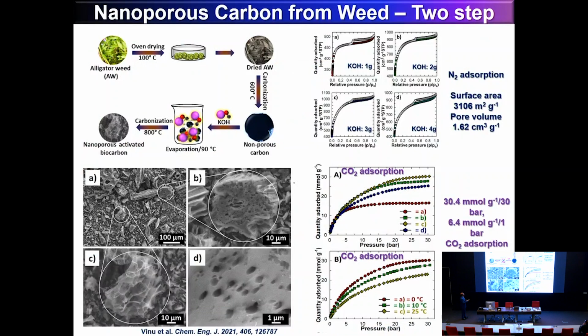When we use this two-step activation using the alligator weed, you see here, you have a completely microporous material when you use less activation. But when you increase the activation, you get both microporosity and mesoporosity with a very high surface area and large pore volume. And what we got in the CO2 absorption is 30.4 millimole of CO2 at 30 bar and 6.4 millimole at 1 bar, right?